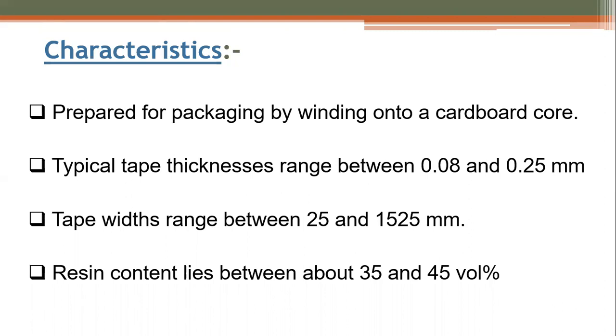Next, tape widths range between 25 and 1525 mm, that is up to 1.5 meters. That is 2.5 centimeters to 1.5 meters. The tape width ranges between these two values. And the last one: the resin content lies between about 35 to 45% by volume. So the resin content is only 35 to 45%. The remaining is the solid and reinforcement particles. So these are the characteristics of the prepreg method.